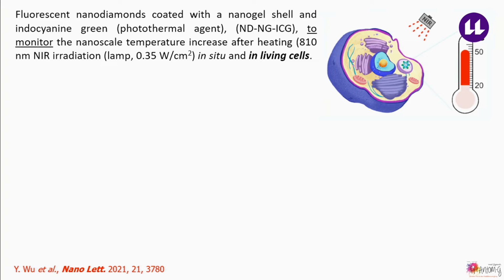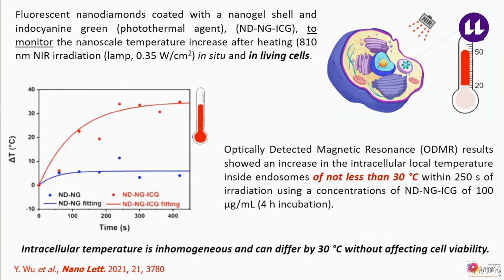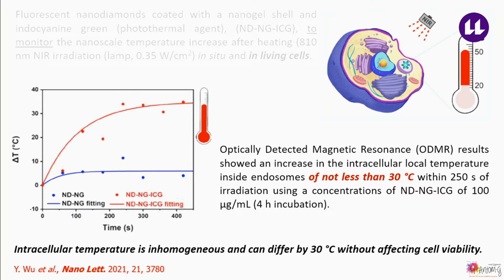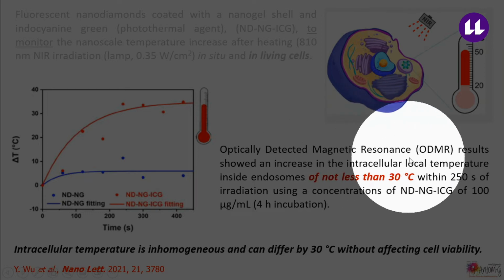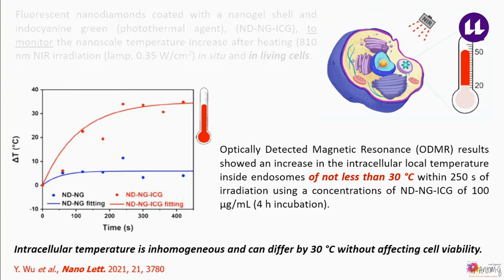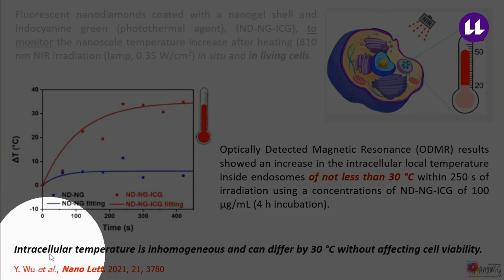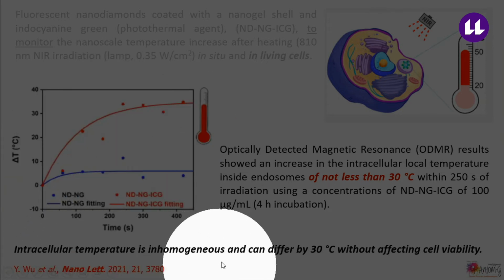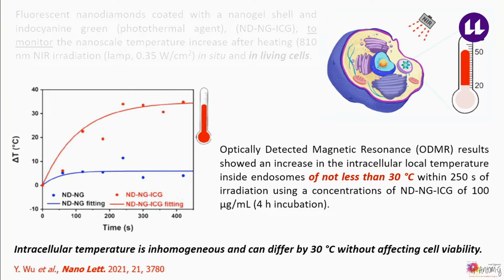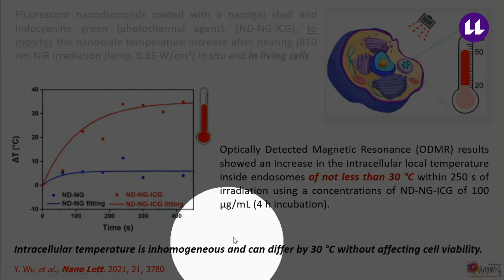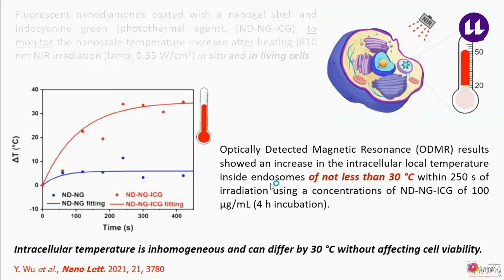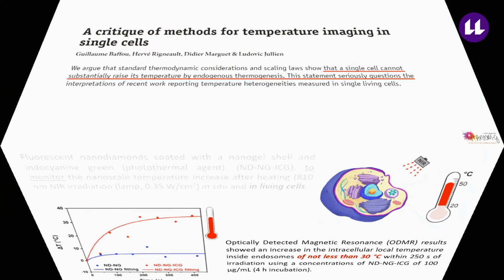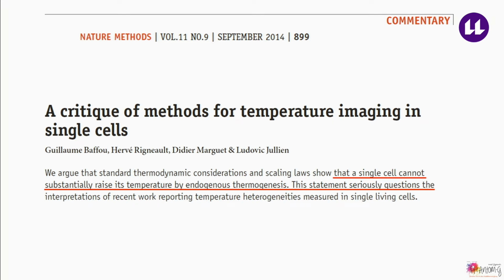intracellular temperature gradients, the authors here use a nanodiamond. They increase the temperature exciting the system with near-infrared irradiation, and they detect the increment of temperature using the optically detected magnetic resonance. And what the results show is that there is an intracellular temperature increase which is inhomogeneous, okay? And they estimate that increment of the temperature inside endosomes, because the particles, the nanodiamonds, are incorporated in the endosomes. So that increment of temperature was not less than 30 degrees. Okay, then these are two examples of the experimental results.